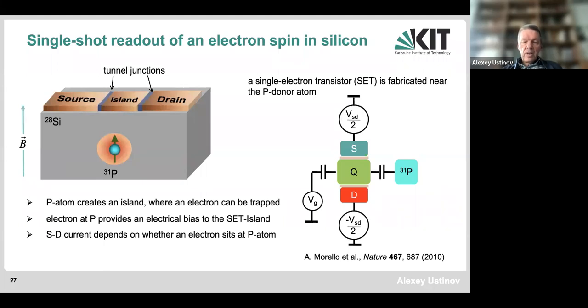So basically, you can fabricate this kind of device using metallic electrodes. Typically, people use aluminum and then use electron beam lithography to form an island of the size of, let's say, a few tens of nanometers. And this island will have a capacitance in the range of a fraction of a femtofarad, actually some couple of attofarads. And this kind of capacitance is already sufficient to create an appreciable Coulomb blockade, which will be seen in this device at low temperatures in the absence of large thermal fluctuations.